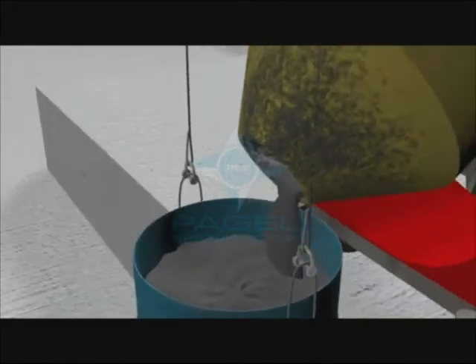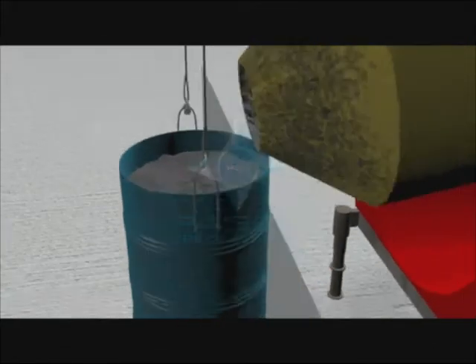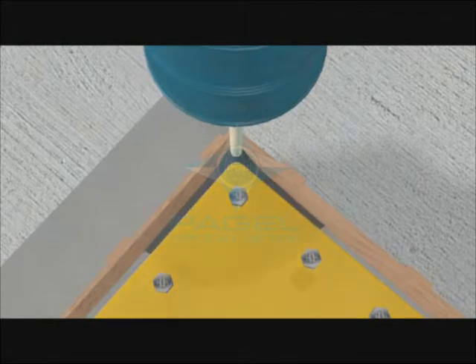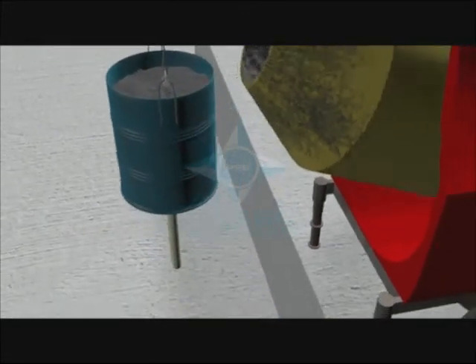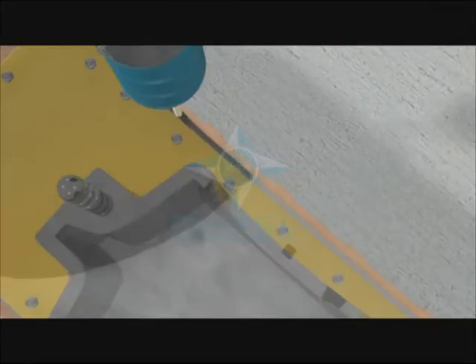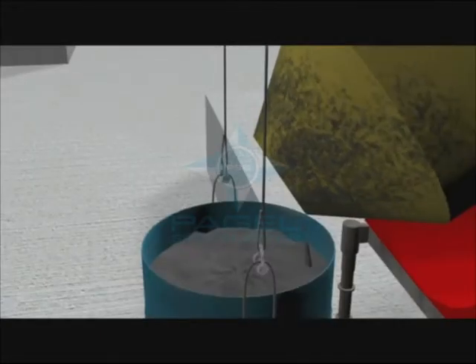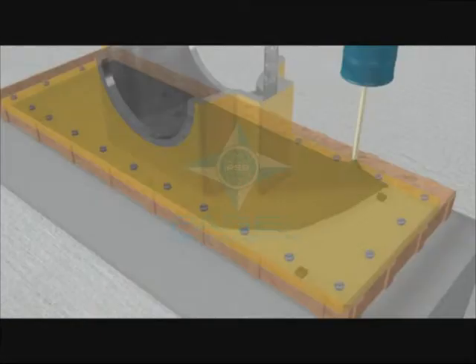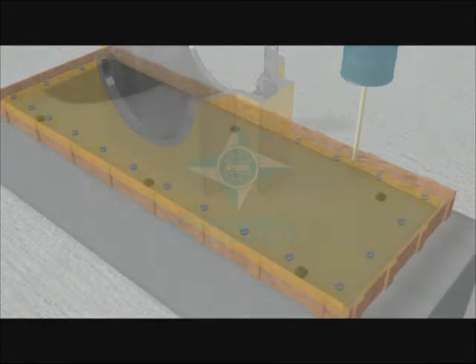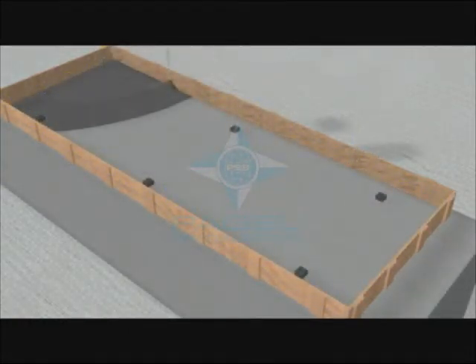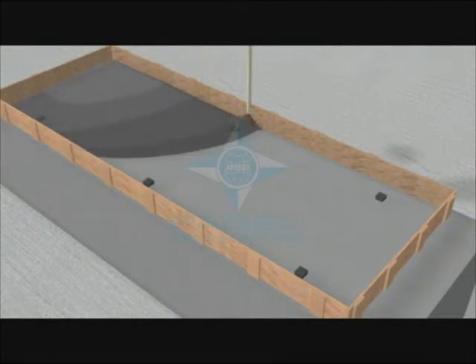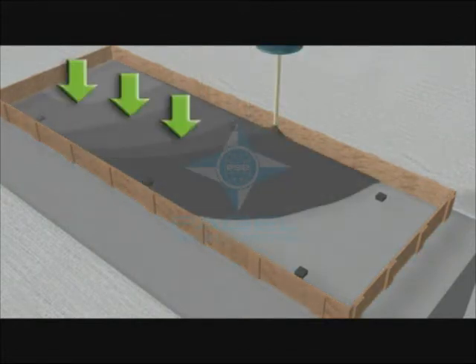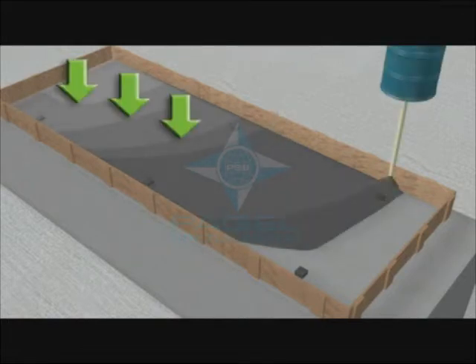The proper method for pouring the grout is from one end of the machine so that air pockets and voids are avoided. For large foundations, the pour from one end to the other will usually take more than an hour, sometimes as much as 90 to 100 minutes. If the grout has low pot life, the first pour will have started to set well before the final pour is done. This can lead to cold joints, which can lead to grout failure.